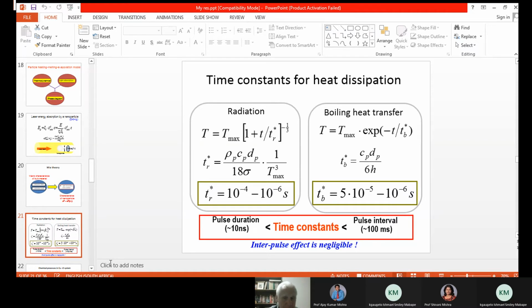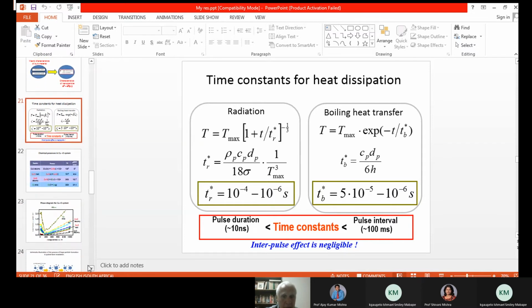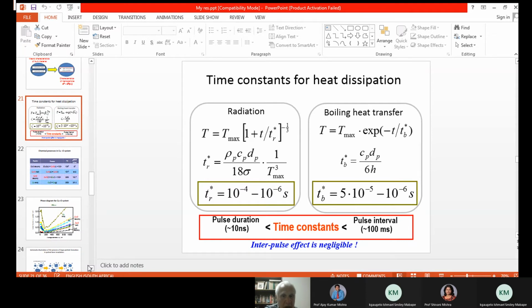So when we finally made a numerical estimation for both main processes, we were very surprised. Very nice result. We could conclude from our estimation that this time is much larger than the time of one pulse. Normally we use a nanosecond pulse laser, and the duration of one pulse is 10 nanoseconds. So you see, this time is much longer than the 10 nanosecond duration of one pulse. It means during one pulse, there is no heat dissipation, no heat loss. So all the energy which the particle absorbs from the laser pulse is spent only on thermodynamic processes: heating, melting, evaporation, nothing more. No heat loss, no heat dissipation.